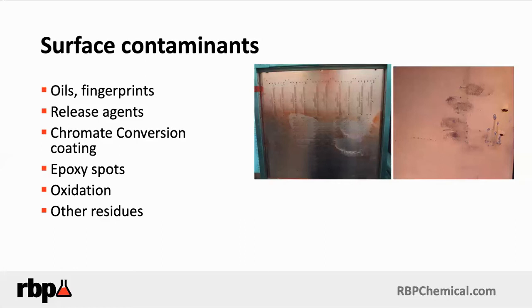Another one of my favorites is epoxy spots. They're basically resin being embedded onto the copper surface. And typically you see this in the interlayer fabrication side when the layers are being laid up in the lamination room. Basically, you get some prepreg dust, basically epoxy dust, that gets onto the panels. And epoxy, of course, is very difficult to remove if you don't know it's there. Typically, wet chemistry like microetchants doesn't help. You've got to go through some type of oxidation material like either plasma or alkaline permanganate. But these epoxy spots can also prevent photoresist adhesion, causing lifting, and other situations which will cause problems later in the fabrication process.